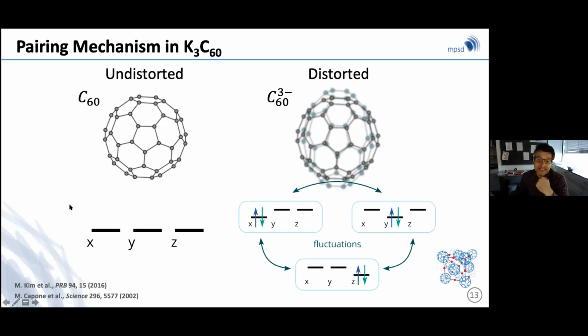There's basically this negative Hund's rule, which favors a low spin state, and is a combination of a Jahn-Teller distortion and electronic interactions, which then mediates superconductivity. It's basically a molecular version of RVB in which fluctuations around the molecule give rise to a superconducting state.